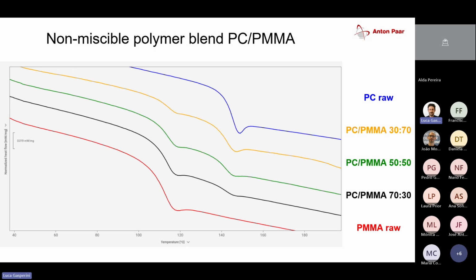How would that look if we had 2 components that create a partially miscible blend? The 2 glass transitions might still be persistent, but they would probably be closer to each other, meaning that from the perspective of changing the specific heat capacity, which is what a glass transition is in a DSC, they affect each other. And if we had a fully miscible polymer blend, those 2 glass transitions would most likely become one. I'm not saying that it would be exactly in between the 2 Tgs of the individual components, but there would definitely be much more effect of one component on the other, and we would most likely see one glass transition step.